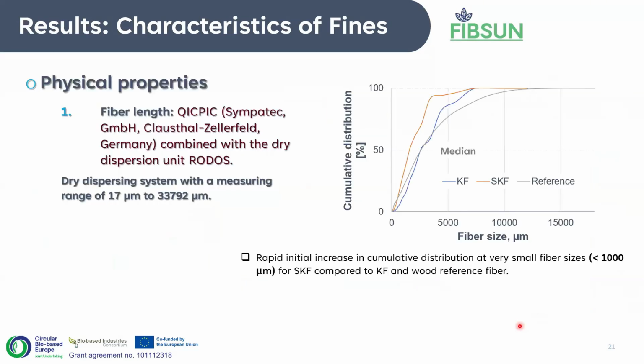Again, when we talk about the material, it is our own interest at SLU to characterize the input material, understand the properties of this material, and how it will influence the final properties of the product. So the first point of call for us was to define the particle size, so the fiber length of what we call the fines, and to compare these fiber lengths to that of the reference wood. And we did this using the QICPIC, which is a device that enables us to feed in these fines. It has different feeders, but for this particular test, we use the dry dispersion unit, RODOS.